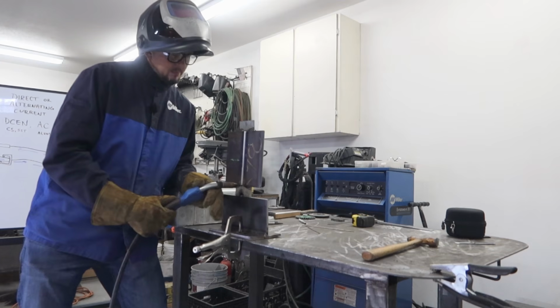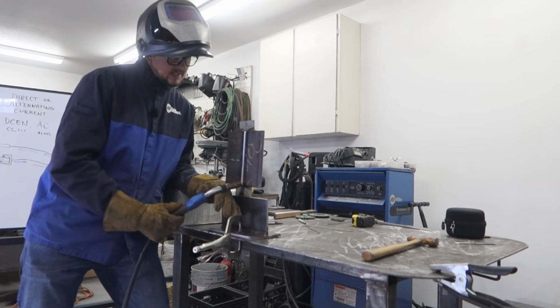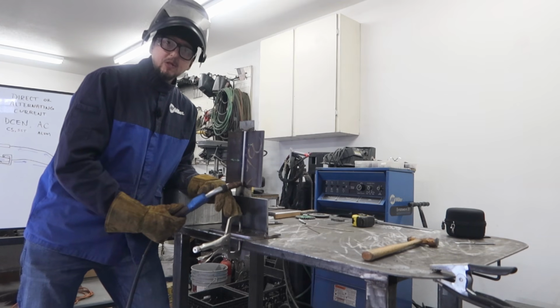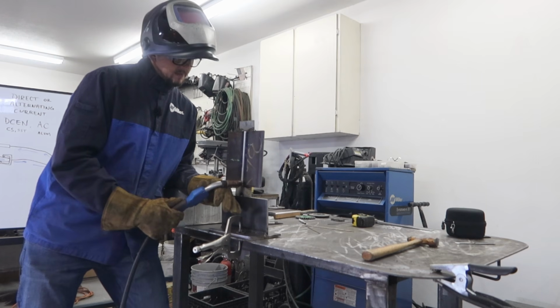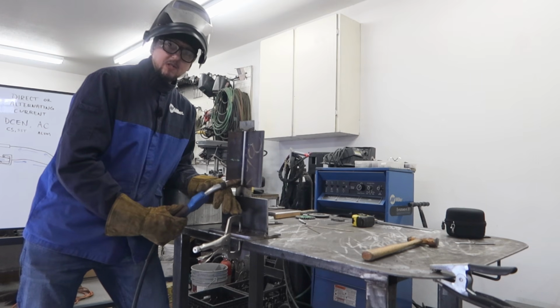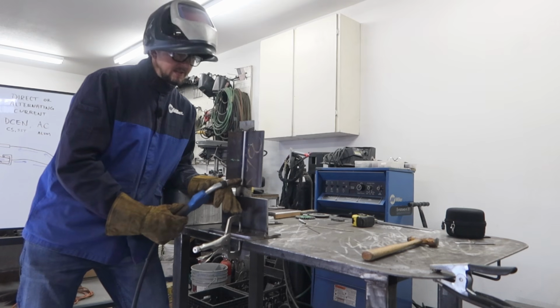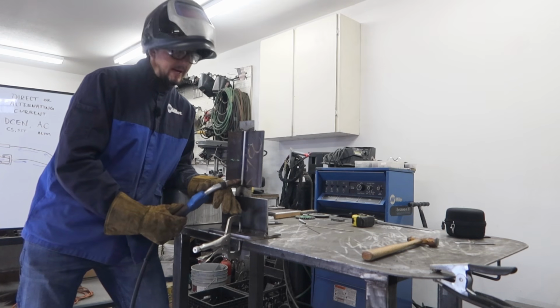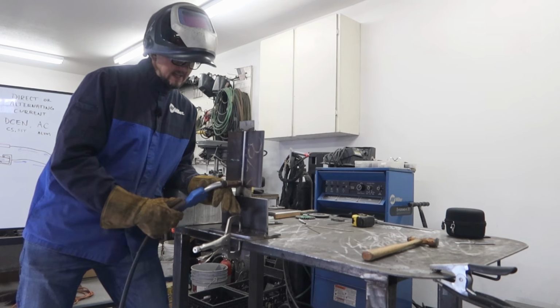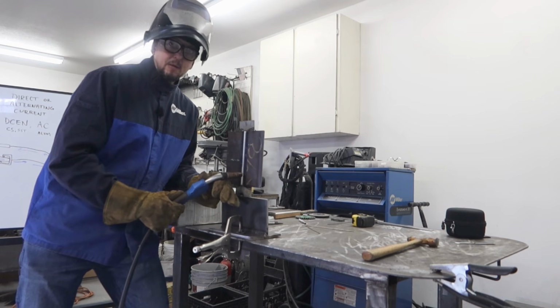The other thing that's important is not using too much of a push angle on this root. For our other passes, we're going to transition to a slight, about 20-degree push angle. But for this root, in order to not get any whiskers coming through the backside, we want to be right at 90 degrees and stay in that puddle and not get ahead of it. Okay, so let's go ahead and give it a shot.